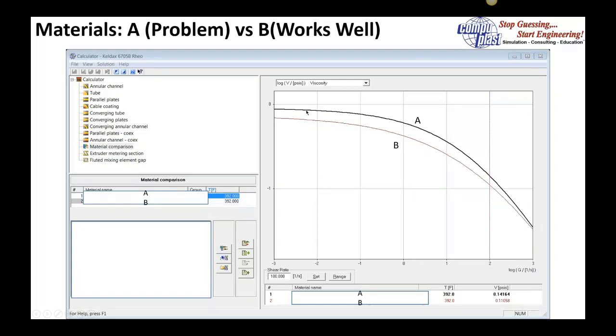This is one of the other reasons we often recommend to people to get the shear viscosity curves as opposed to just using a melt index. A melt index is one point represented somewhere at the low shear rates. By having the complete shear viscosity curve, you can compare materials more precisely and see that in the processing range, material A is about 40% more viscous than material B. When you run them in the same screw design, the material that's more viscous generates more shear heat.